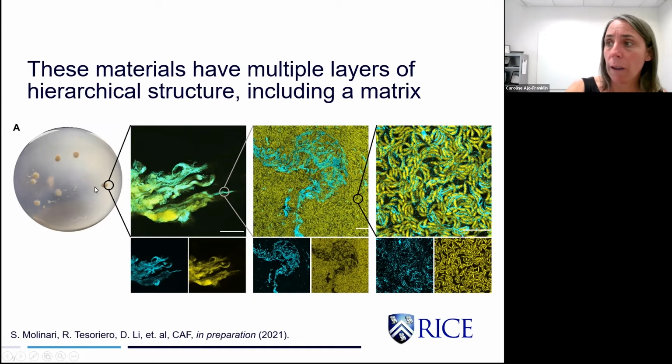So what Sarah Molinari, a very talented postdoc in my group, did is she gently opened up these materials and again stained them with SpyCatcher GFP. And what you see here, at a scale of hundreds of micrometers, is that the GFP and the cells are stained somewhat uniformly throughout the material. So you see both channels